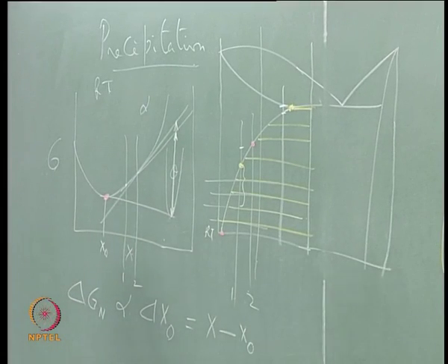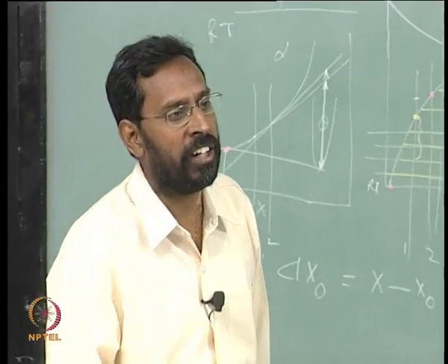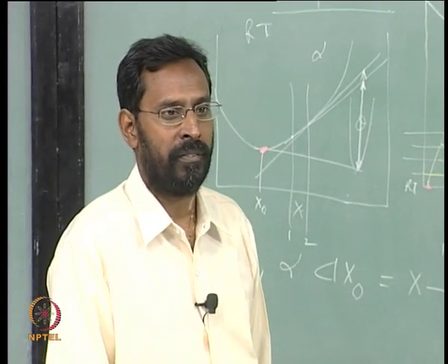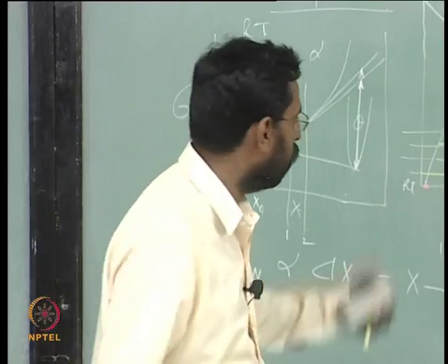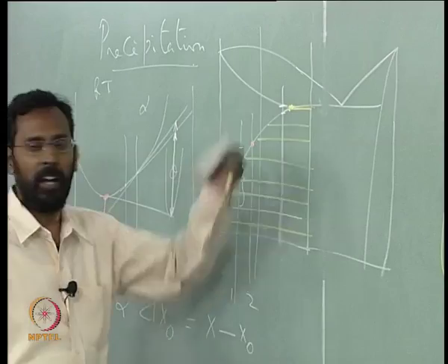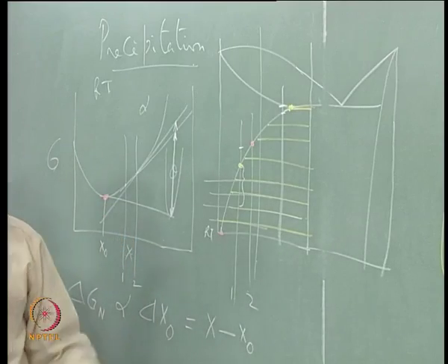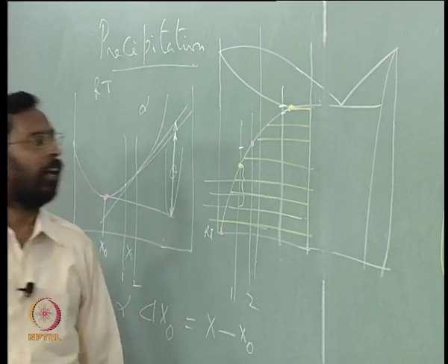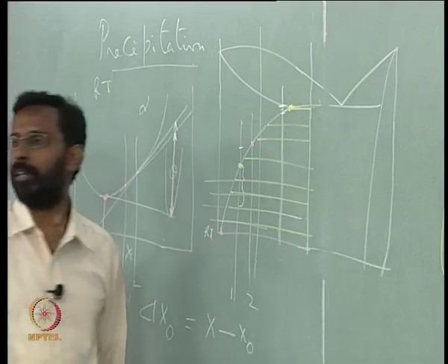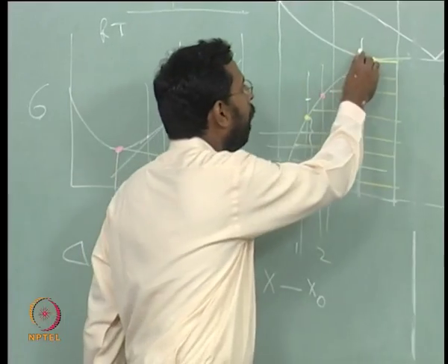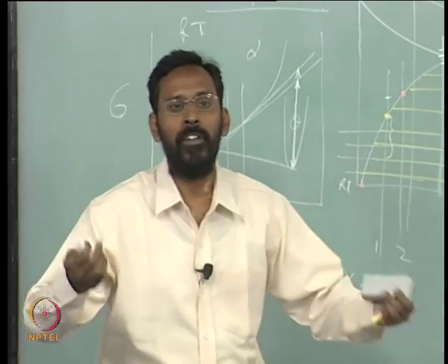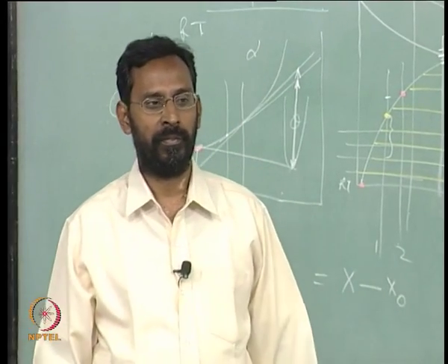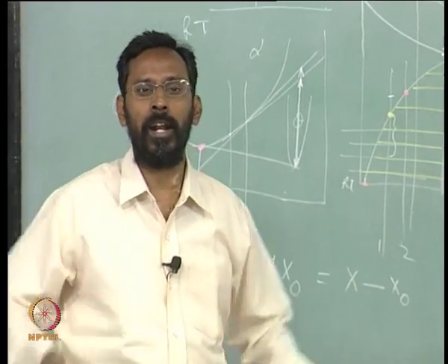When that is very small and you want to do the homogenization treatment, what we call in steels the austenitization treatment, here we call it a homogenization treatment. During that homogenization, if you do not maintain your furnace temperature carefully, you end up in this domain. Once you end up in that domain, some liquid forms, and the liquid usually forms at the grain boundaries.